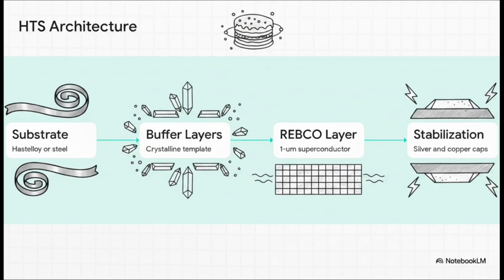First, you start with a flexible metal substrate, something like Hastelloy, just for mechanical support. Second, you deposit a series of buffer layers to stop metallic atoms from bleeding into your superconductor, and crucially, to create a perfect crystalline template. Third, using vacuum deposition, you grow a 1 micrometer thick superconducting ReBCO layer that perfectly copies that aligned template. And finally, you cap the whole thing with silver and copper to stabilize it electrically. Every single layer has to be absolutely flawless to force those ceramic grains into perfect alignment.